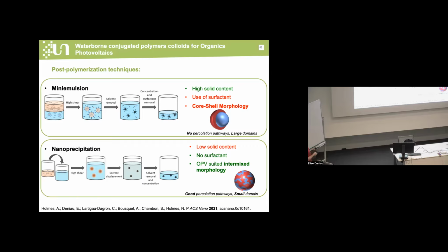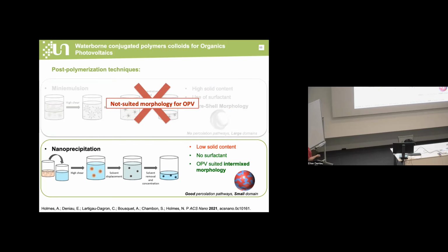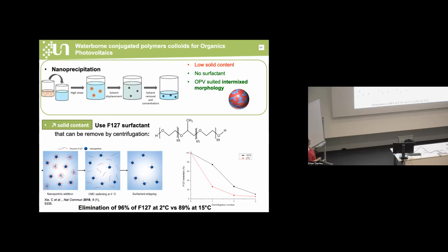Whereas by nanoprecipitation, the solid content is rather low because you don't use surfactant, but the morphology that you get by nanoprecipitation is more intermixed, which is more suitable for OPV application. So that's why we use nanoprecipitation in order to form the nanoparticles of semiconducting materials. But in order to overcome the limitation of a low solid content with nanoprecipitation, we still decided to use a surfactant, but we decided to use the